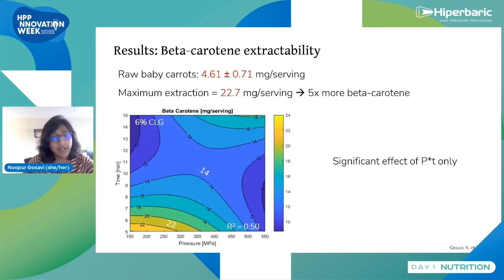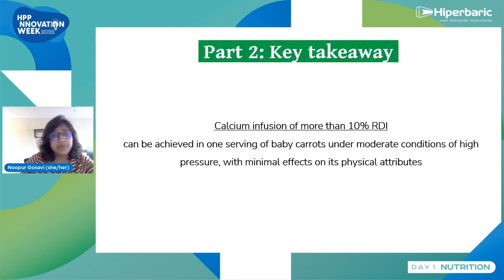For beta carotene, the amount of extractability in high pressure processed baby carrots was actually 5 times more as compared to raw baby carrots, which can possibly translate into higher bioaccessibility of beta carotene. So from the first part of my research, we showed that we could use high pressure processing to infuse more than 10% of the daily requirement of calcium in baby carrots.